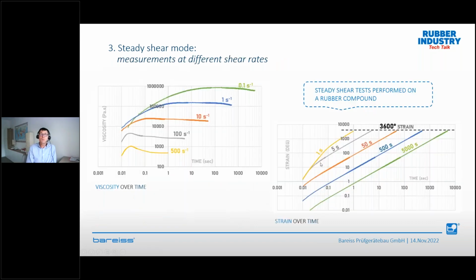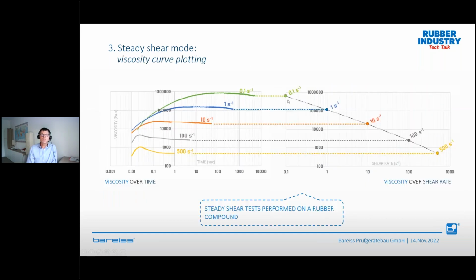So when we are doing the motor, what I mentioned before, up to 3,600 degree of arc means 10 rotations at different time, means different speed, means different shear rate. So we are running at, for example, 0.1 reciprocal seconds, 1, 10, 100, and 500 reciprocal seconds shear rate. Yeah? And then you get this curve. We have this overshoot, and then going into these steady shear conditions. So when we plot these steady shear conditions and transfer them to the right side and plot the viscosity as a function of shear rate, we get these very, very nice